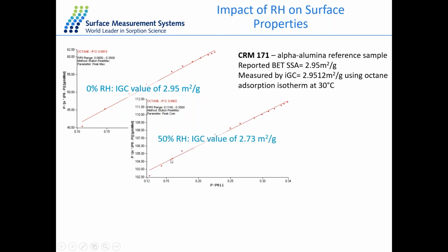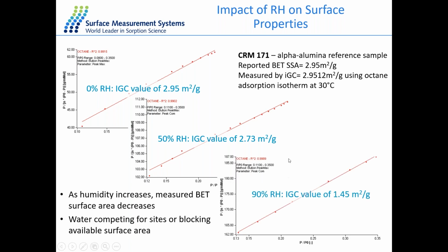We've then repeated the experiment at 50% RH. So we're increasing the experimental conditions to 50% relative humidity and carrying out the BET experiment. As a result, we see a slight decrease in our BET surface area. We've also carried out another step, 90% RH, and again we see a further decrease in our BET surface area. So what we can understand is that when we introduce water to our sample, water is competing for the sites for our octane to interact with, and therefore we have a continuous decrease in surface area. It's a very interesting experiment to understand how humidity affects the surface of your sample.